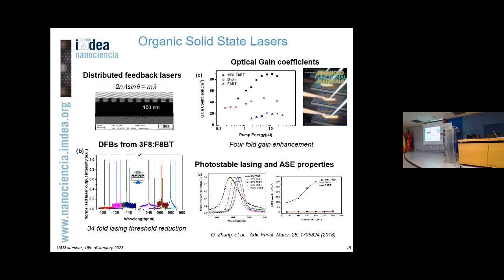So this has to be 90 degrees. If you put 90 degrees here, then the refractive index, you know it more or less, then you can obtain this. This is the pitch that you require. So the pitch required goes very much with the diffraction order you want to exploit. Ideally, one would like to exploit maybe the first order of diffraction because you have the highest diffraction efficiency, but the problem is that requires the smallest pitch, and technically that's sometimes difficult—gratings with 70 nanometers, 50 nanometers separation. We normally go to the second one.